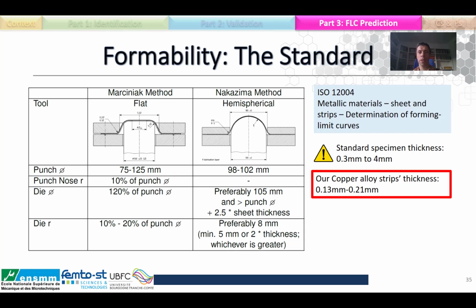ISO 12004 takes care of the determination of forming limit curves for metallic material sheets and strips, to be precise. It also recognizes two experimental methods to obtain the FLC: the Marciniak and the Nakazima methods. The standard covers the rules for geometry of the testing device and for the strip thickness. Unfortunately, the rules don't cover our sheet very well, because the standard specimen thickness has to be between 0.3 and 4 millimeters, and the punch diameter is from 75 to 125 millimeters, and our copper alloy strip thickness is between 0.13 and 0.21 millimeter, with a width of 15 millimeters or 30 millimeters maximum.